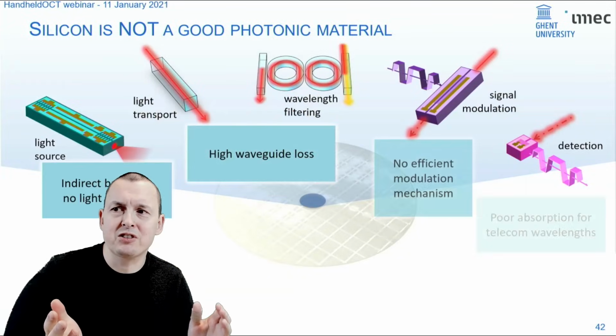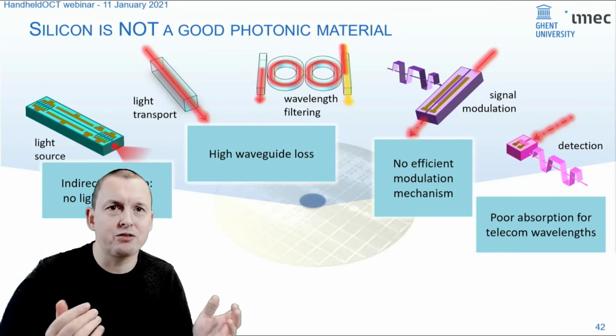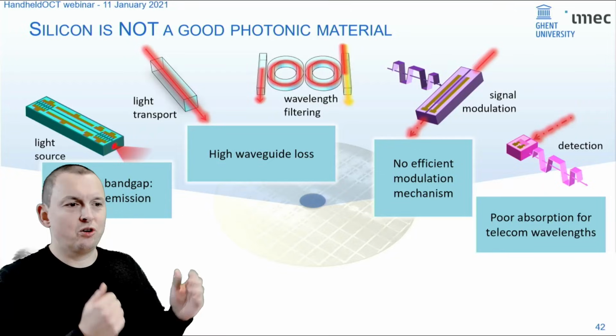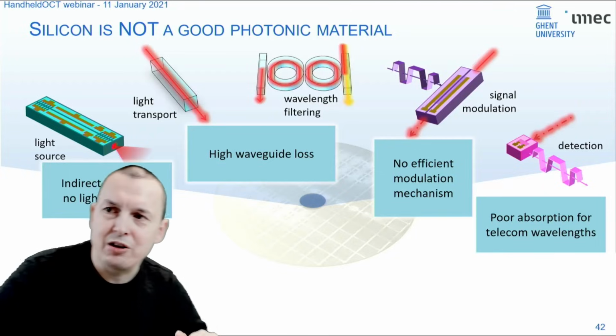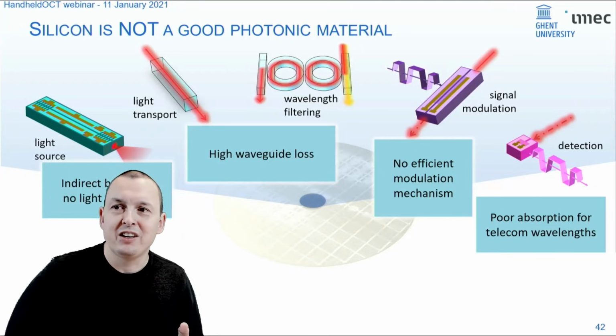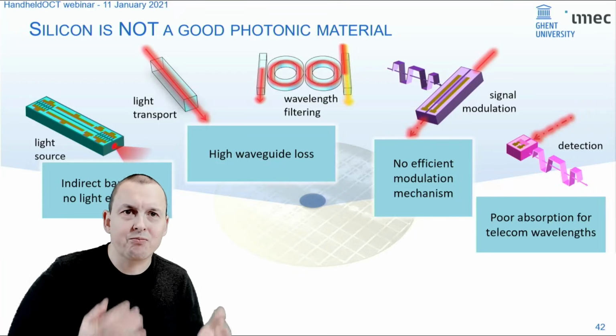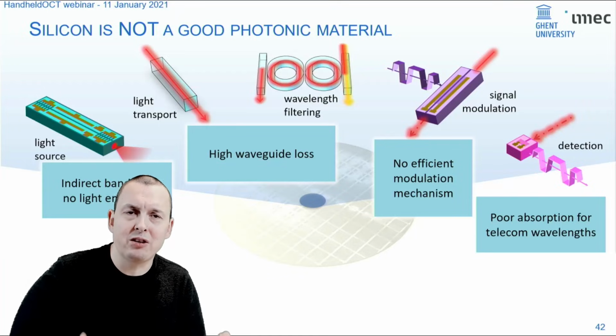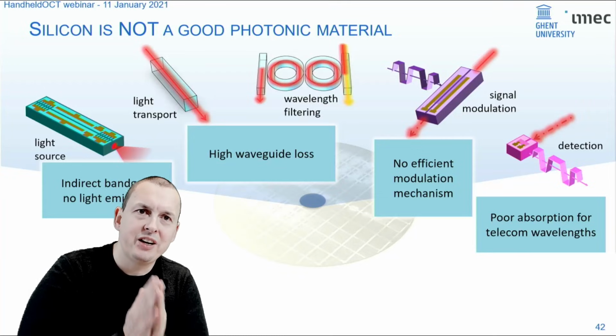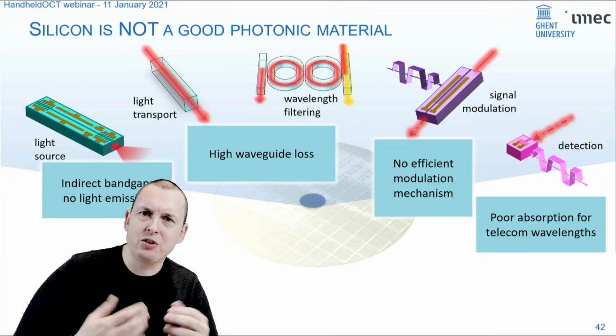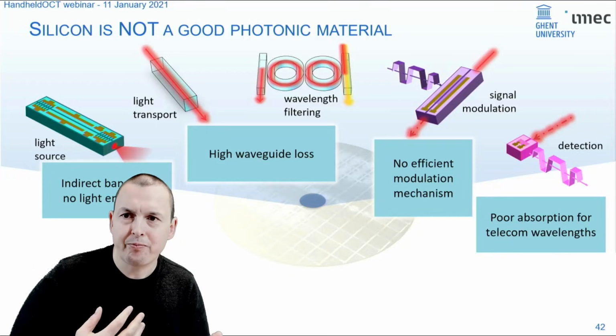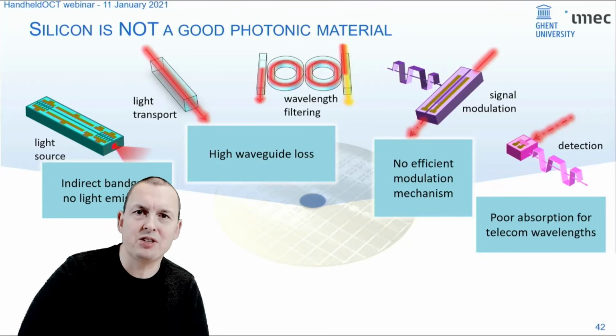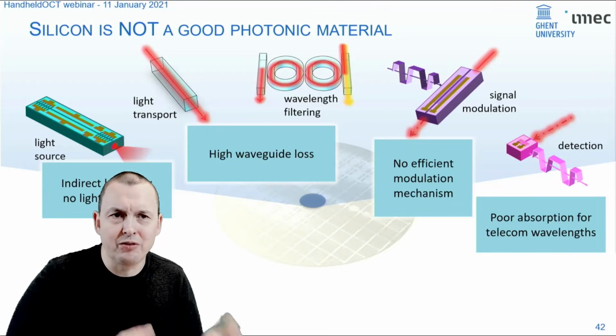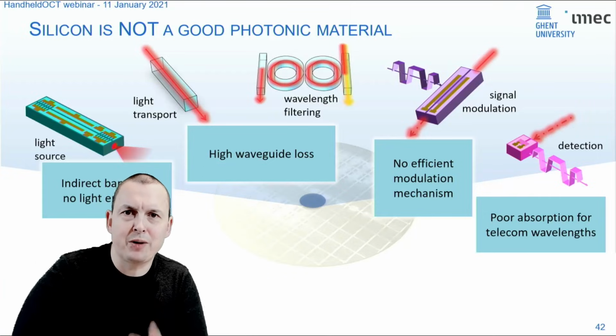If you look at it on first sight, silicon is really a bad material for photonic integrated circuits. It has no direct band gap, so making a laser source out of it is really not that easy. If you want to use it as a waveguide, okay, the material itself is quite low loss, but fabricating it in such a way that you don't get a lot of absorption or a lot of losses is not that easy. There's no efficient modulation mechanism in silicon. And also, if you're using it for telecom wavelengths, silicon is transparent, so it has poor absorption for telecom wavelengths. So why would you want to use it?